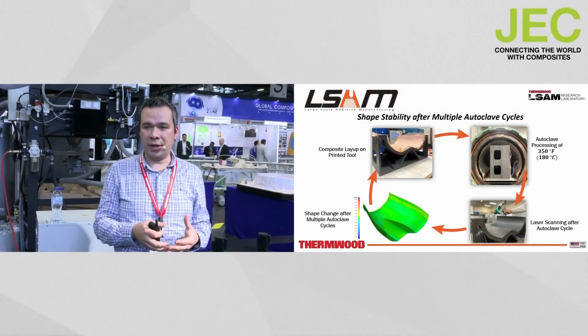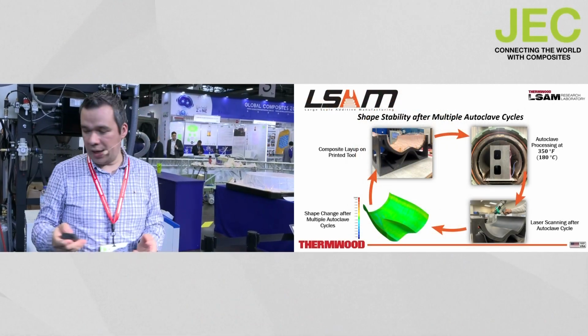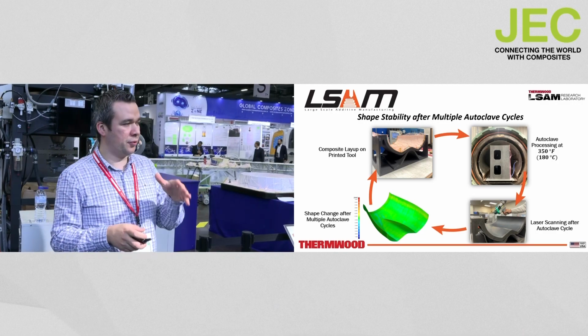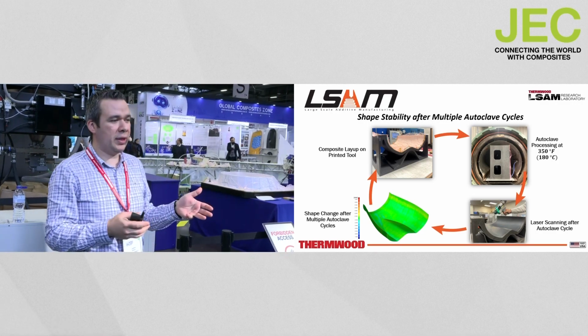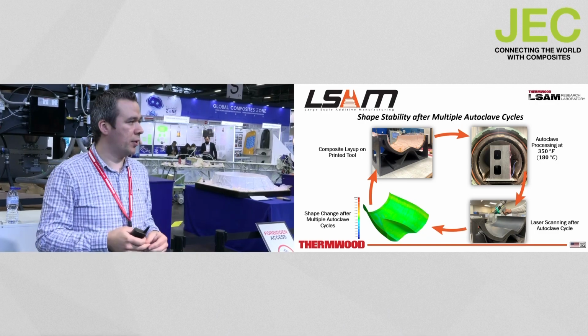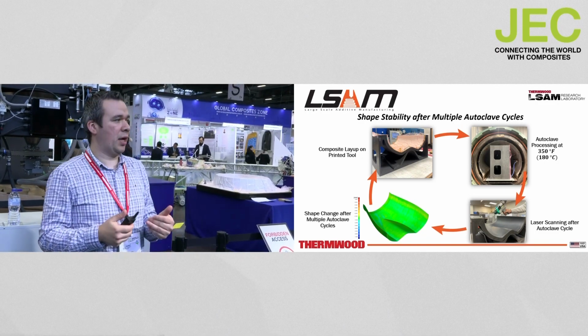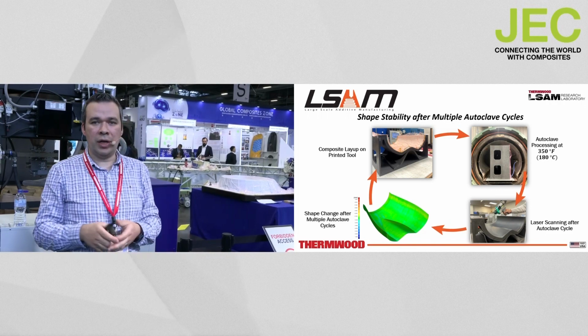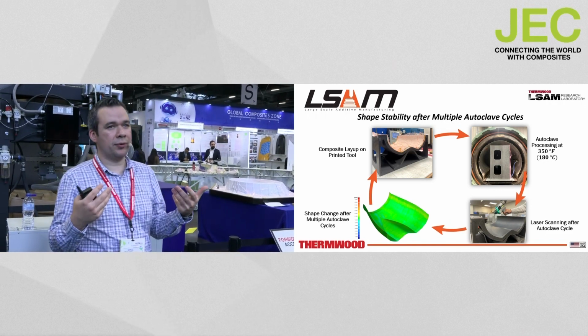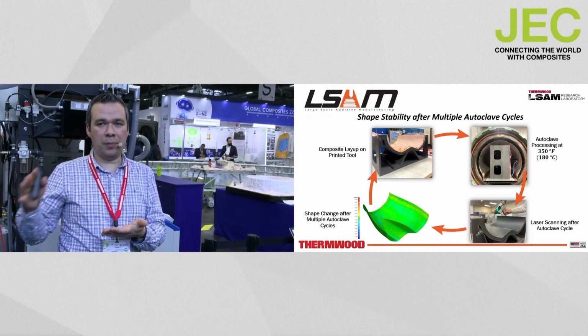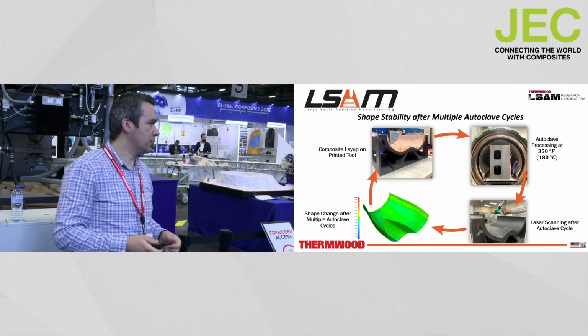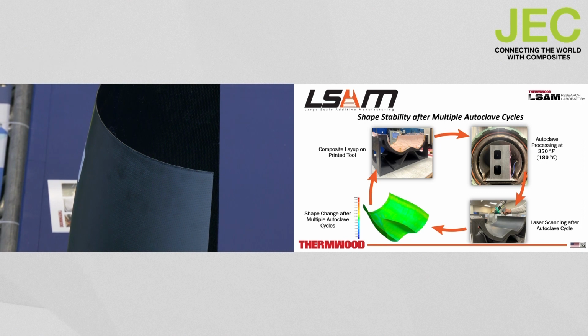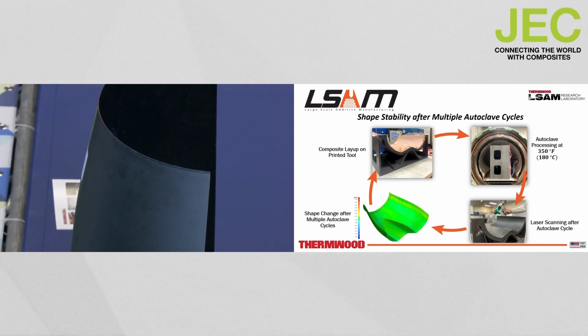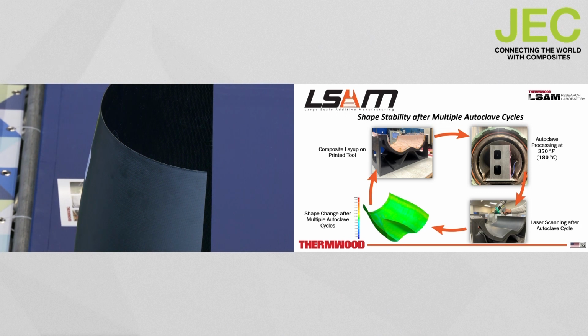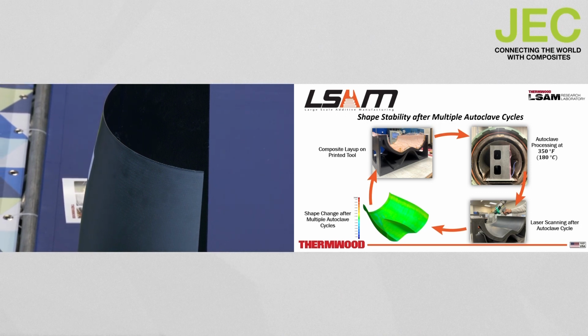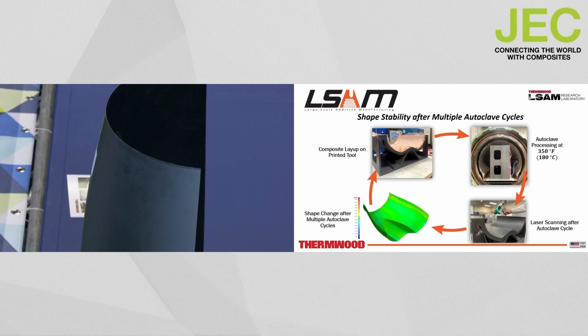Looking at this particular set of tools that we have demonstrated, we also did a shape stability study where we made composite layups on the surface of the tool. We cured them in an autoclave at 180 Celsius. And after each autoclave cycle, we laser scan the surface and carry out a deviation analysis to look at the shape stability over multiple autoclave cycles. As you can see here in this plot, most of the deviations that we observe after multiple cycles are fairly stable and within the range of less than 100 microns of change.